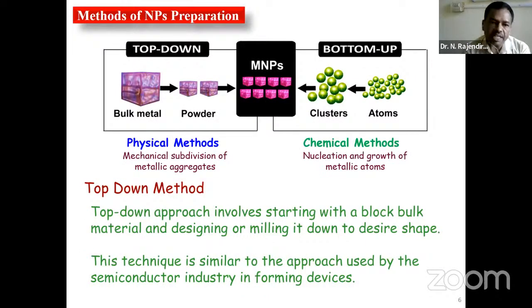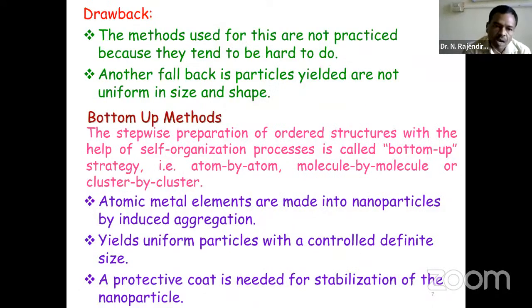Normally, nanoparticles can be synthesized by top-down as well as bottom-up approaches. The top-down approach uses physical methods, that is, mechanical subdivision of metallic aggregates. Whereas the bottom-up approach is a chemical method, that is, the nucleation and growth of metallic atoms. The top-down approach involves starting with bulk materials and milling them into the desired shape. This technique is similar to the approach used in the semiconductor industry for forming devices. However, this approach is not widely practiced because it is very hard and needs sophisticated instruments. Another drawback is that getting uniform-sized particles is very difficult in these physical methods.